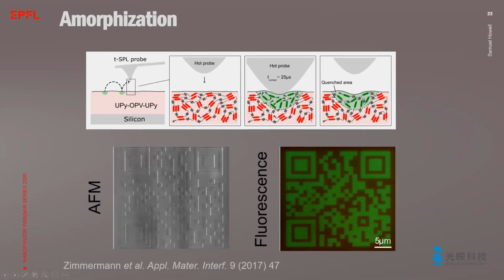However, at the nanometer scale, when a heated tip is used to heat only small volumes, the heat quickly dissipates into the sample after the probe has been removed. Quenching of this high temperature state can induce a permanent fluorescence contrast. This is an example where the high heating rates of TSPL are important, and I assume that there will be other materials that exhibit such a behavior that is not possible at the macro scale.